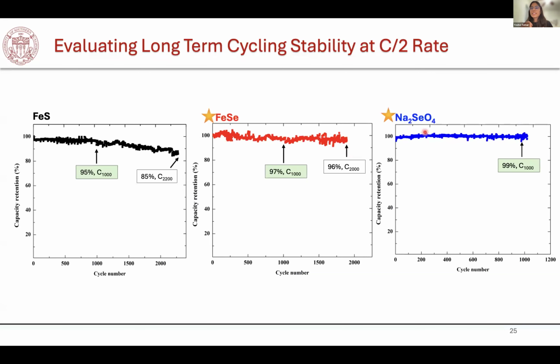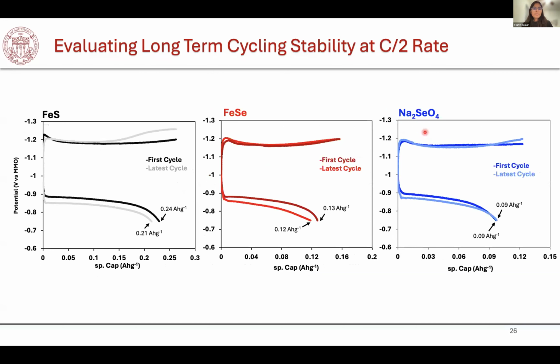And similarly, when the selenium is present in the electrolyte, we again see good capacity retention. I'm still cycling these cells and taking data on them, and they're performing really well. And at last, I just wanted to compare the polarization curve of these life cycles for the 3 electrodes that I was studying. And as you can see here, for all the 3 cells, the polarization curves compared to the very first cycle to the very last cycle, that is the 2000 cycle, the polarization curve has